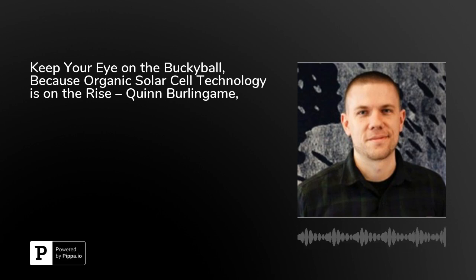So if I want to absorb all the light in the visible, I can do that with maybe 100 nanometers of an organic material, where if I want to do that in silicon, I need several microns of material. So they're totally different optically, but silicon does a great job. Obviously it's in integrated circuits everywhere. It's a great conductor of charges. So they do just fine in that sort of thick form factor. They're able to get charge extracted, no problem. And in organics, because their conductivity is so much lower, we're the ones who have to work a bit harder. That's one of the main challenges in our field right now, to get the conductivity and the charge mobility of organics up to a level where we can actually extract charges out of a device.